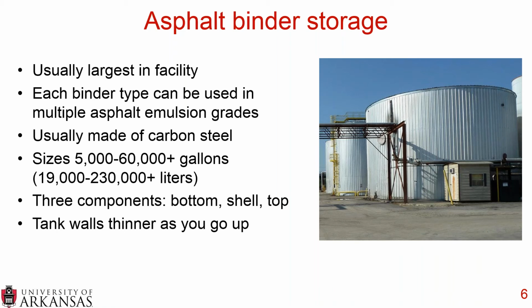And the tank walls actually get thinner as you go up. That makes sense because you have less pressure toward the top because there's less head pressure of the material within the tank. And then finally, a very important component is you do want a pressure release at top. That's because when you're filling the tanks, you want air to be able to escape. When you're emptying the tanks, you want air to be able to come in. You don't want those tanks to collapse or have the top pop off on you.